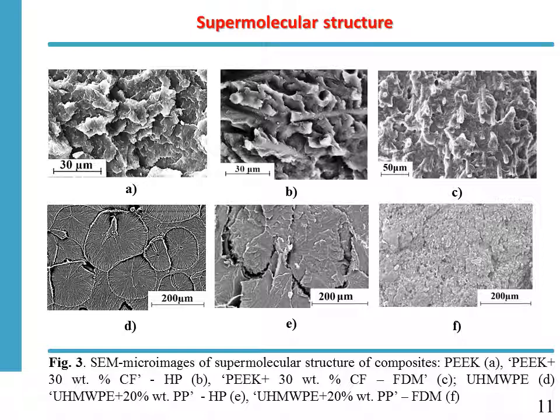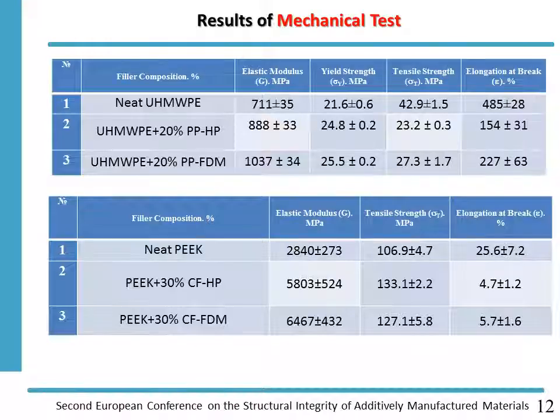At the bottom of the slide you see the micrographs for ultra high molecular weight polyethylene, that is, for the neat polymer. This one is a composite with a mixture with 20% polypropylene, and on the right the same composition produced by fused deposition modeling, and in the center produced by hot press.